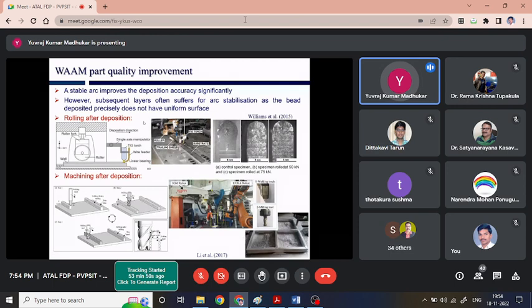Now, in order to increase the mechanical properties of the WAAM process, if we dig into the literature, we found some literature on enhancing the mechanical strength of it. In one paper, this is what they have done. Once they are depositing using the TIG torch, the wire is fed over here. A mechanical roller is being used at a certain zone, when the bead is already at an elevated temperature, at a certain load.